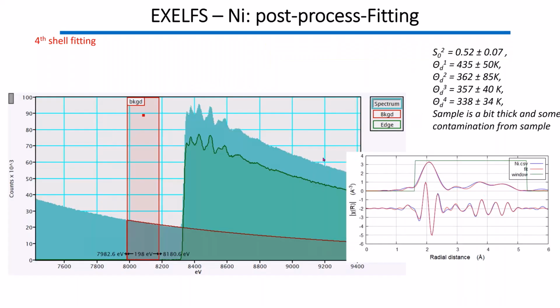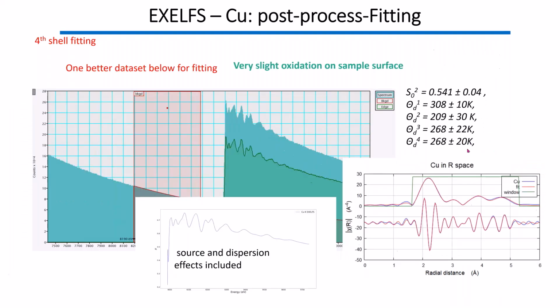And of course, you can also apply this to other materials, which we tried. Another one, nickel, for which we on purpose picked a data set that is not as good, where you have a contamination on the sample surface, and you can see the fitting is not as good as you are expecting, although it does give us a proper trend for the Debye temperature. And if you manage the experiment properly and choose the optical settings properly, you would be able to fit the radial distribution function properly up to the fourth shell, especially looking at the real part, which is the criterion for the fitting, and you can see a similar trend.